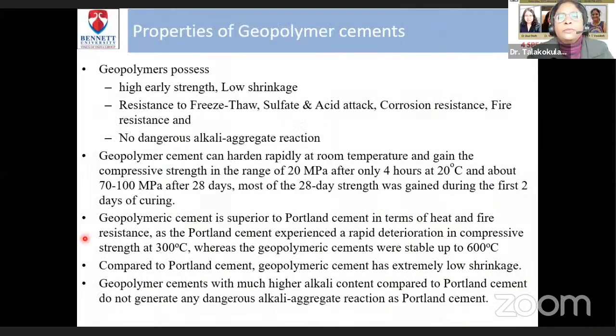And if you compare the mechanical and hardened properties of geopolymer concrete, it possesses high early strength. You can get the required strength in 3 to 5 days using geopolymer concrete, whereas ordinary Portland cement concrete would require around 28 days. Resistance to freeze thaw, sulfate attack, corrosion, and fire resistance are all improved compared to ordinary Portland. There's no dangerous alkali aggregate reaction in geopolymer concrete. And you can see the geopolymer cement can harden rapidly at room temperature and gain a compressive strength in the range of 20 MPa after only 4 hours.